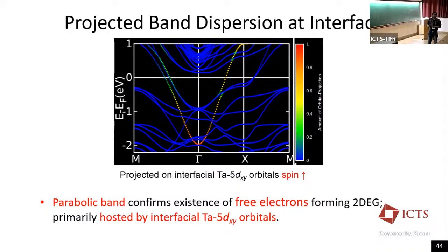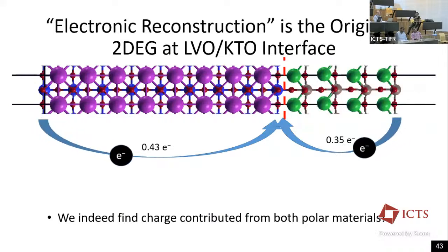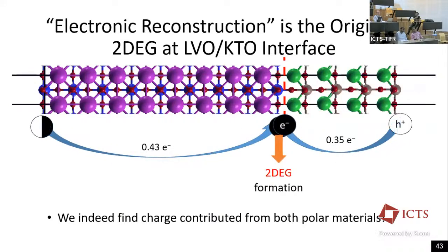Yeah, for example, if I compare this with standard III-V semiconductors, let us say gallium arsenide, the best carrier density you can have is like 5e12 or so, right? And this has an effective mass of like 0.05 or something, and you're talking about 0.1, which is not too far from that, but your carrier density goes up to 10^14. Yeah, so as I showed, in the ideal case, half an electron should be transferred from the surface. I agree with that, but there has to be some states which will support these electrons, right? So where are the states coming from? Because it's a very sharp band.